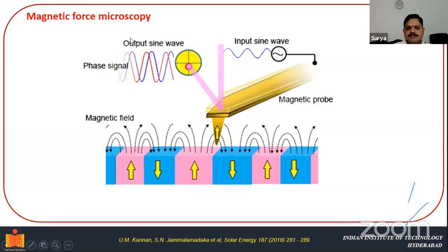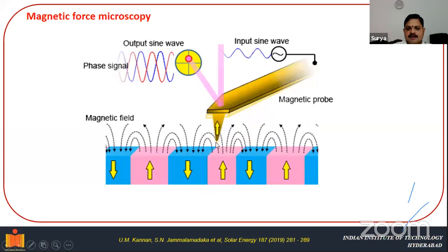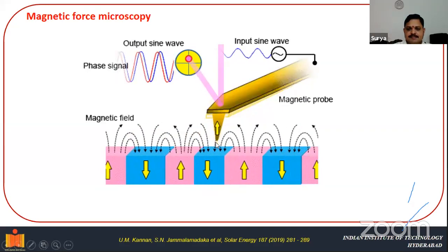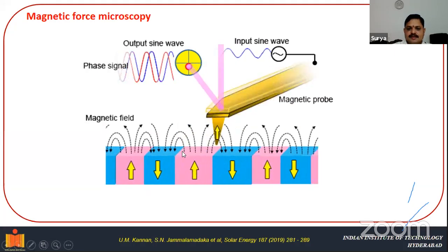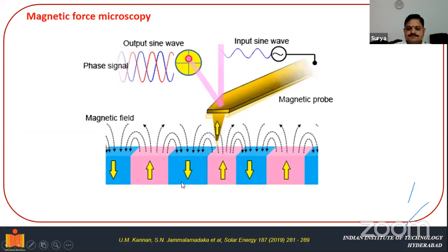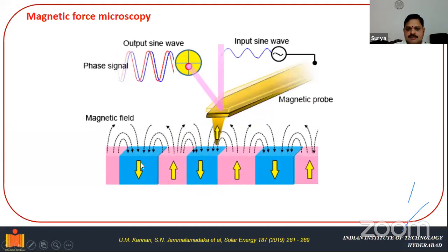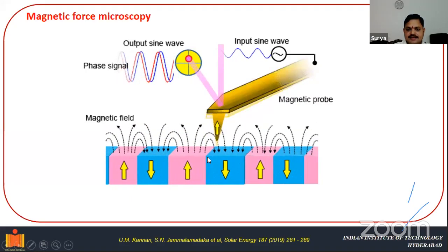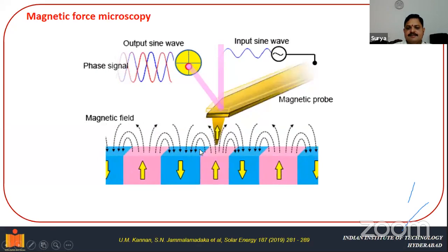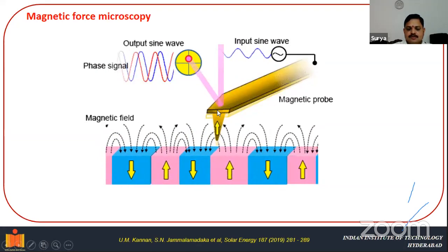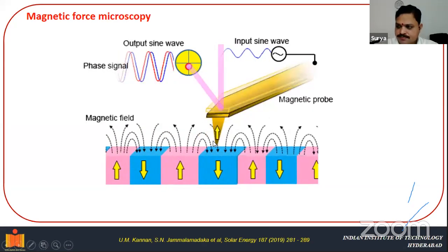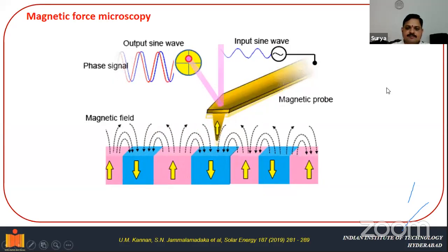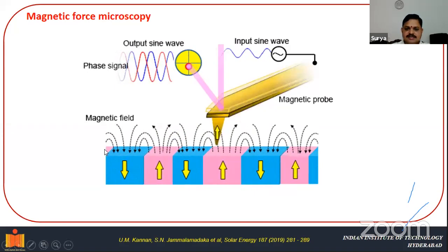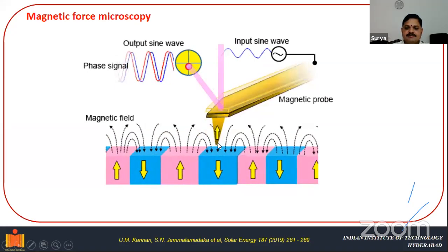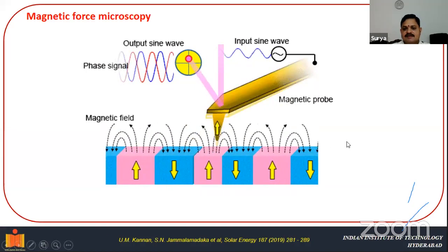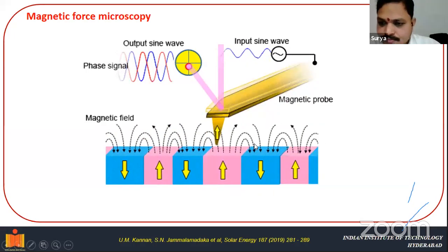In a magnetic force microscope, instead of a non-magnetic tip, you will have a magnetic tip. When you try to image a magnetic material, as we know, it will have domains and domain walls. Wherever a domain ends, your stray field starts, and again it will start at another domain. This kind of magnetic flux lines you can find on the magnetic material. When you bring a magnetic tip towards a ferromagnetic material, the force lines emanating from the tip will interact with the force lines on the ferromagnetic material. So there will be interaction between the flux lines of the tip and those of the ferromagnetic material, which will give the magnetic interaction.